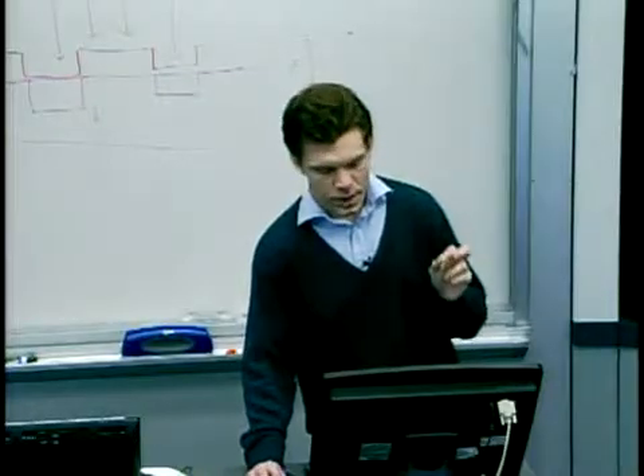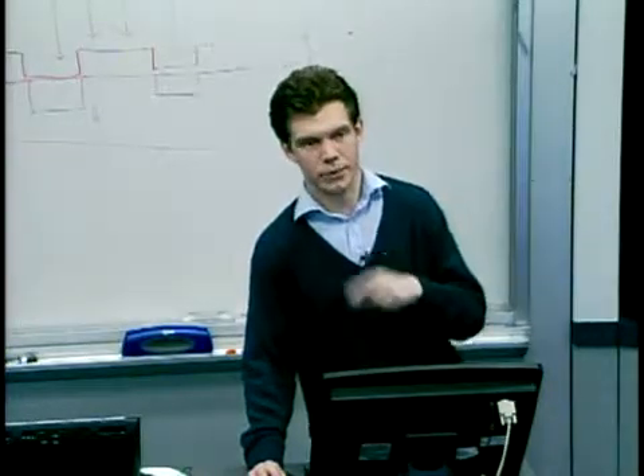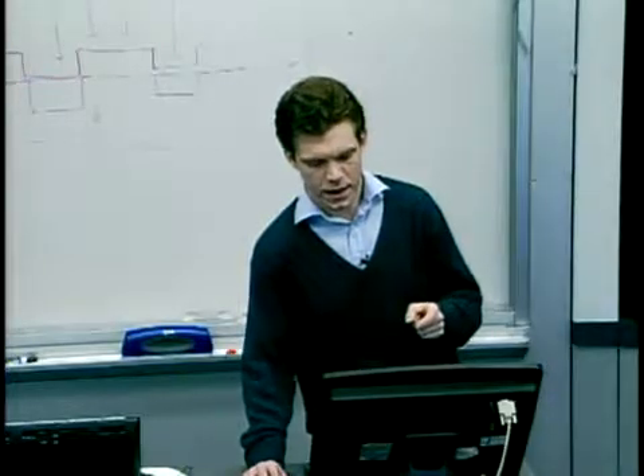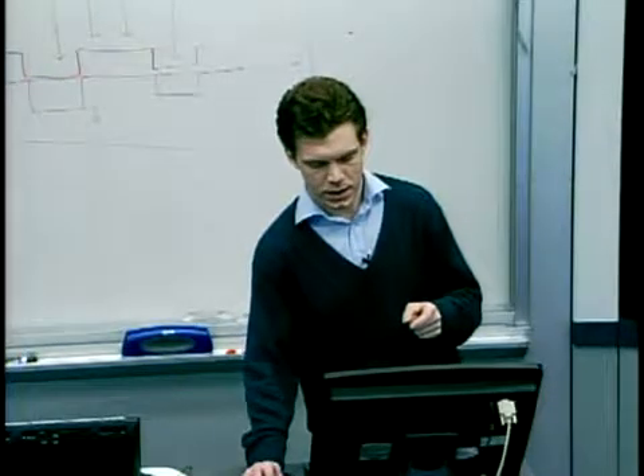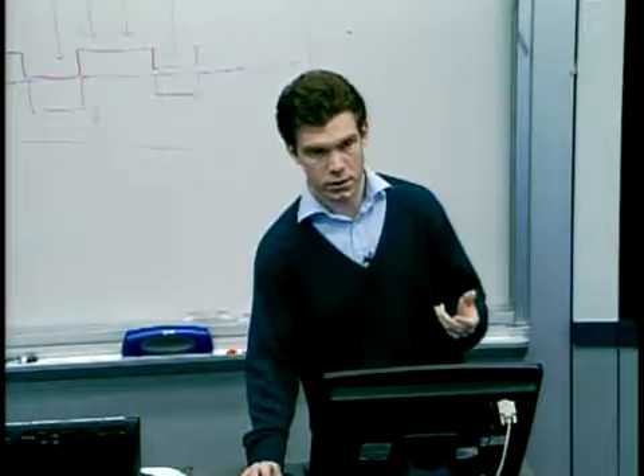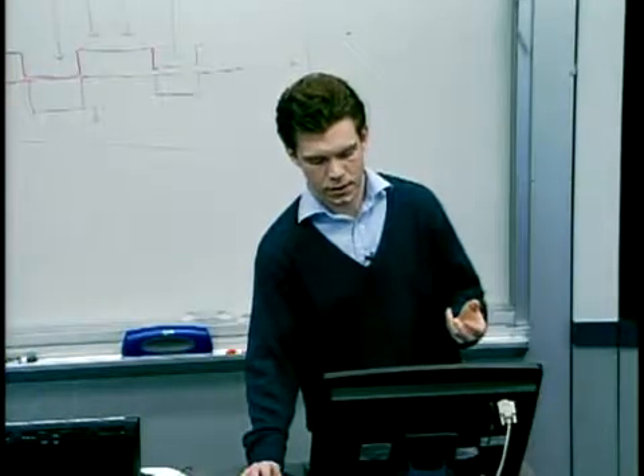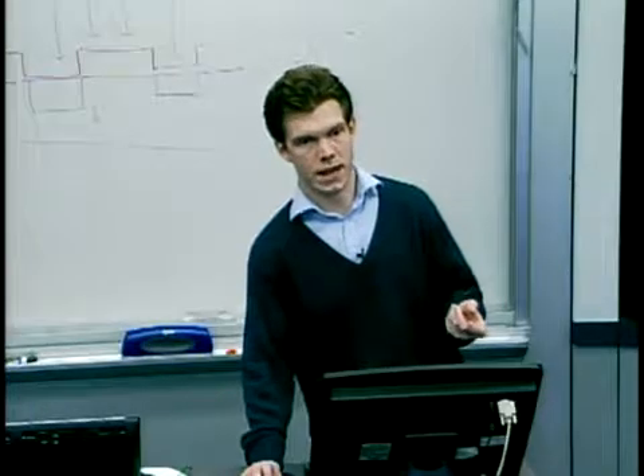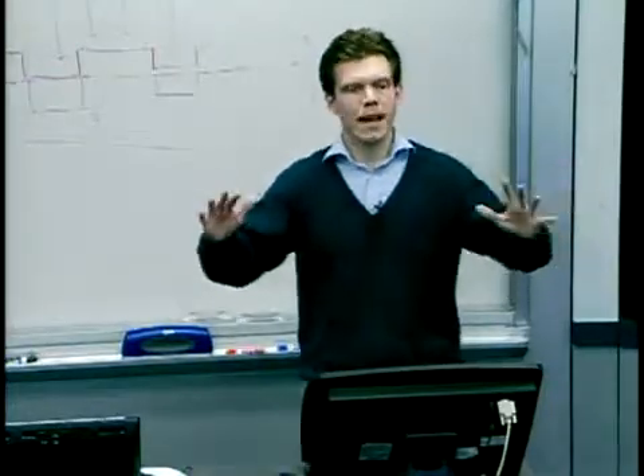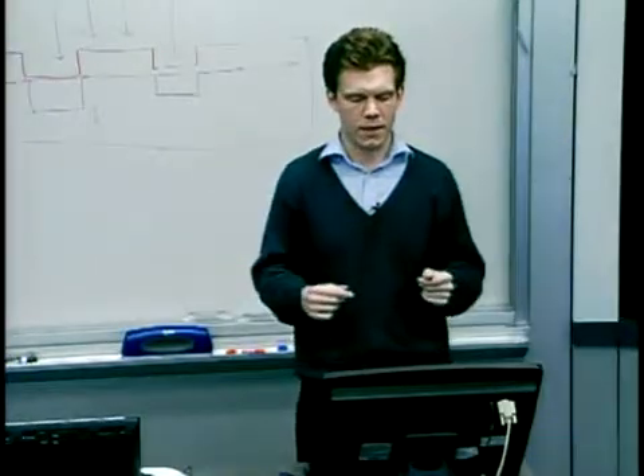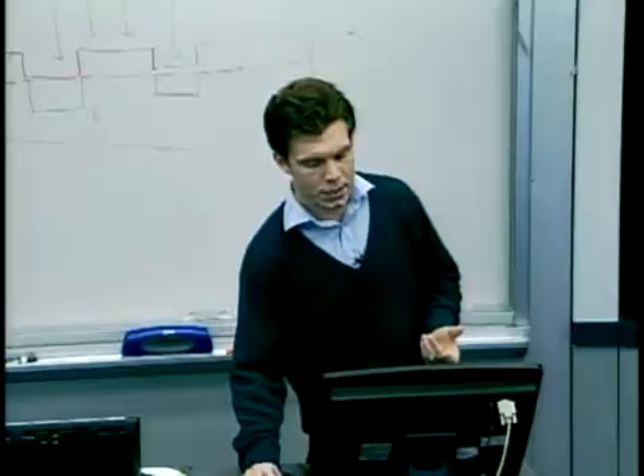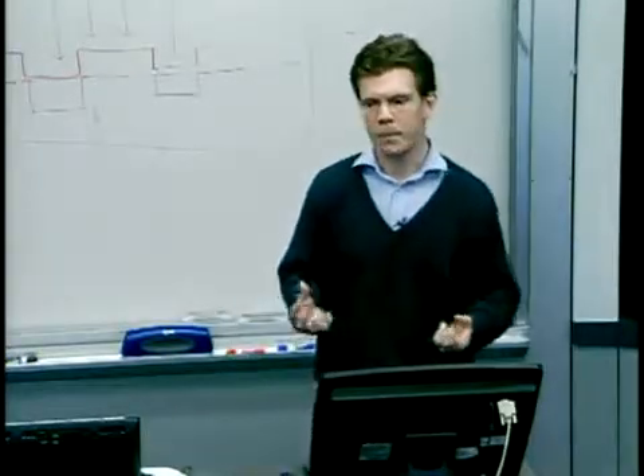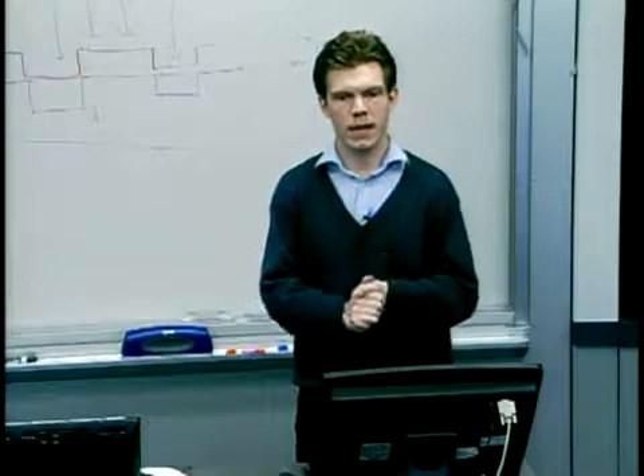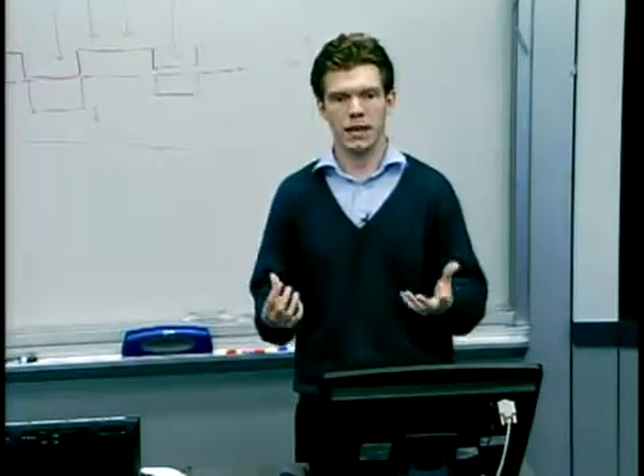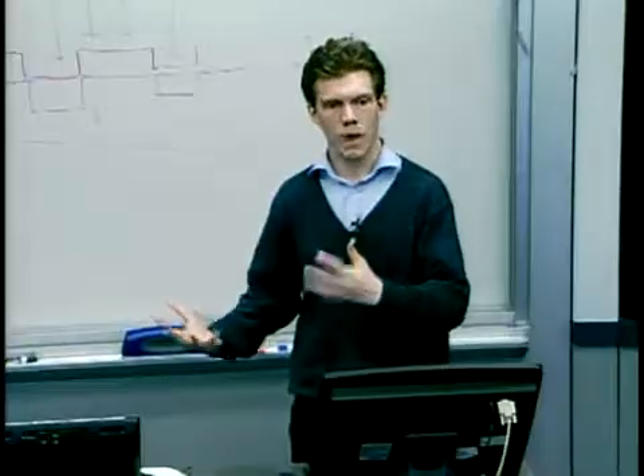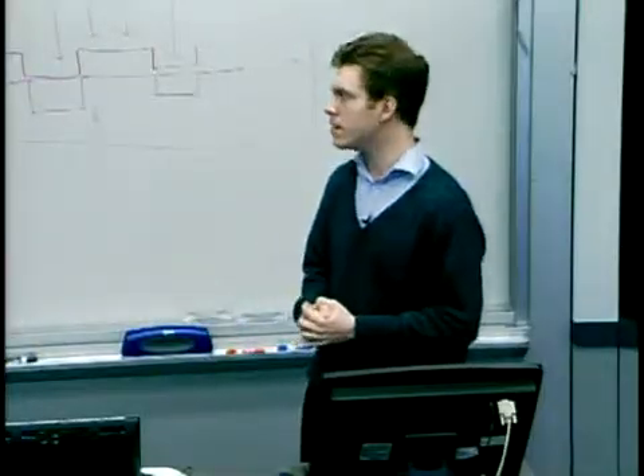However, if you don't cool down before you remove the load, and that's what is shown on the right, then we see this recovery. We see the material springing back almost to its original shape, and so there's a very small residual compressive strain in that case. And just looking from a distance at this simulation, which is done at a particular temperature, 140 degrees C, essentially the material is behaving in a spring-like way, predominantly. Most of the deformation is recovered without cooling it to freeze that deformation in place.